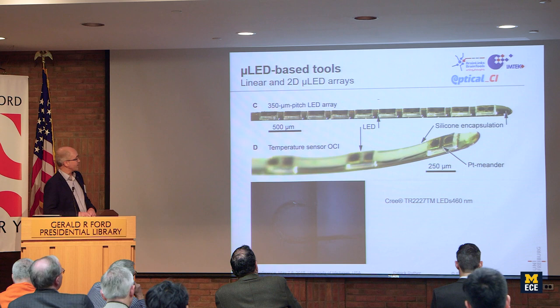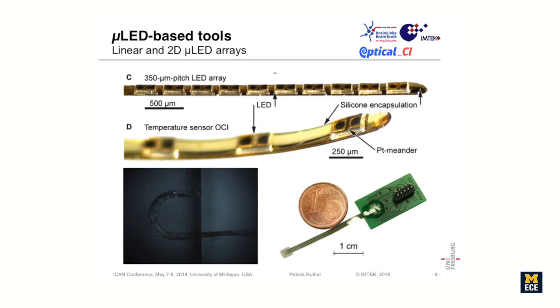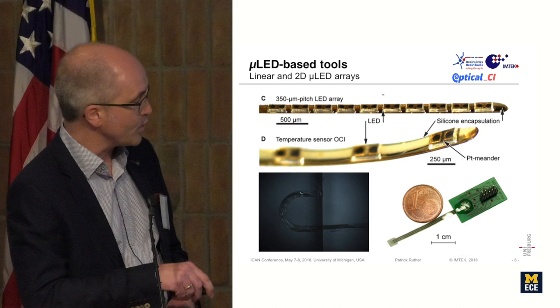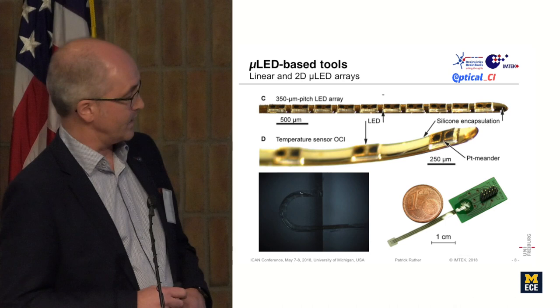Yeah, this is how the device looks, a bit more in detail, or a bit enlarged. So here you see these commercial LED chips from Cree emitting at 460 nanometers. We can make them highly flexible, and that's illustrated here, hopefully, with our probe in a dummy cochlea, bending the probe by a radius of 500 micrometers, and it's still functional.